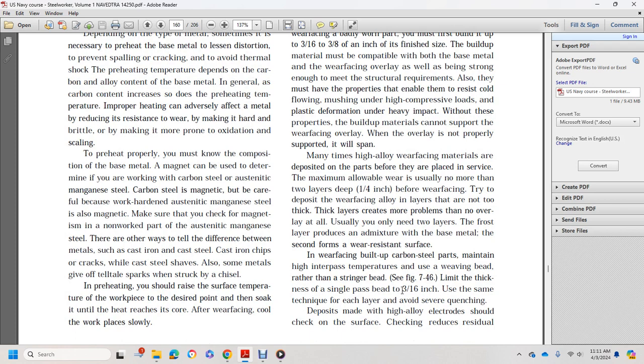Many times, high alloy wear-facing materials are deposited on the parts before they are placed into service, with the maximum level of wear, and usually no more than 2 layers deep, 1/4 inch, before wear facing. Try to deposit wear-facing alloy in layers not too thick. Thick layers can create more problems. You only need the 2 layers. The first layer produces a mixture of the base metal and the second forms the wear-resistant surface.